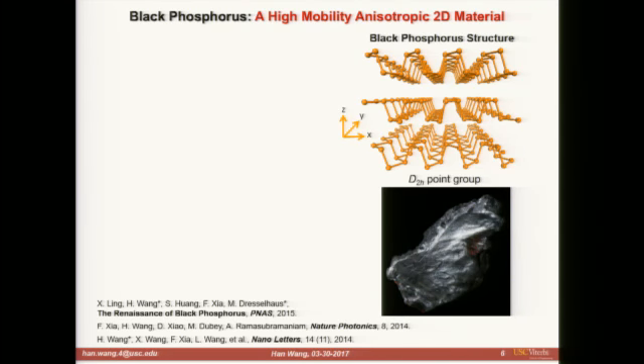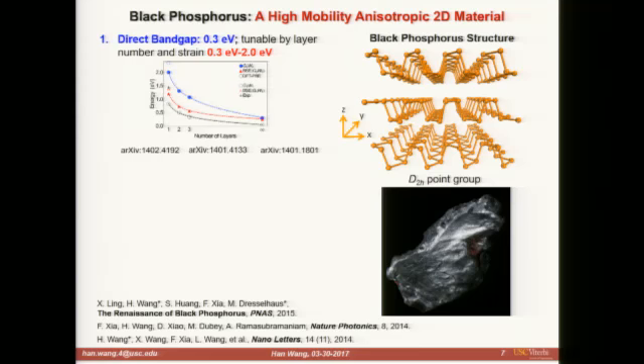This is a picture of a bulk single crystal of black phosphorus. BP in its bulk form has a direct band gap of 0.3 electron volts, and if you thin it down to atomically thin samples, you can tune the band gap all the way from 0.3 eV to above 1.3 eV optical band gap. If you add a little strain, you can push it even further.